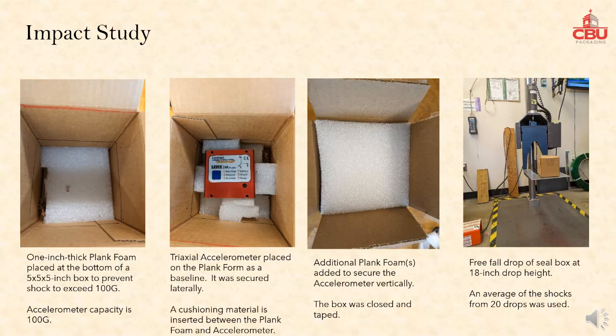A triaxial accelerometer with a 100 G maximum shock was used in this study. A base plank foam was used to cut down some shock, so the acceleration remained within 100 G. A cushioning material is placed between the base foam and accelerometer. The accelerometer was tightened up in a corrugated box to prevent horizontal and vertical movements. The box was dropped at 18-inch drop height 20 times per case.